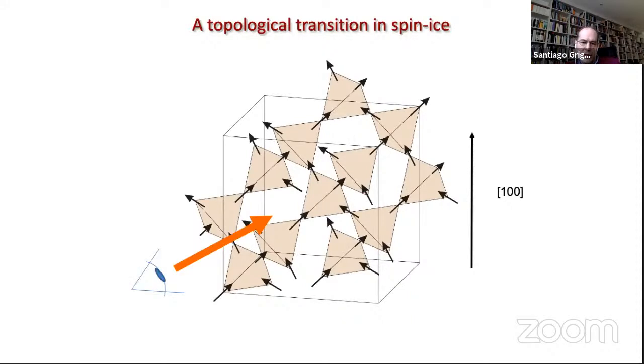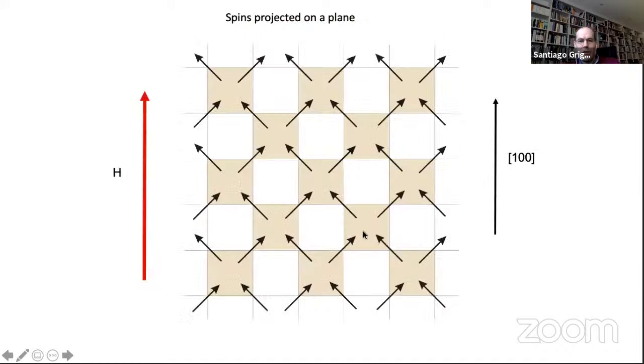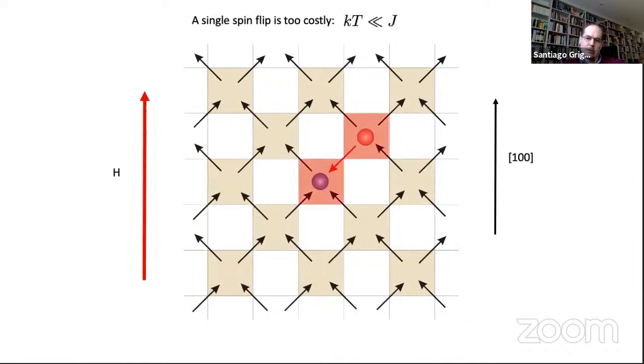Allow me to project this. So this wants to be some sort of an eye. I'm looking in that direction, and now I project this onto a plane, and I'm putting a field along this direction. And as you see, when I do that, I polarize spins all in that direction. But this direction is special in the sense that the configuration I get belongs to a spin ice configuration. You see that in each tetrahedron, these yellow squares are the tetrahedra, I get 2 spins pointing in and 2 spins pointing out. So essentially, the field not only is not going against, but it favors the ice rules.